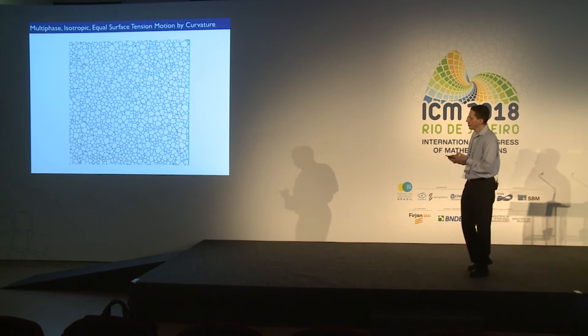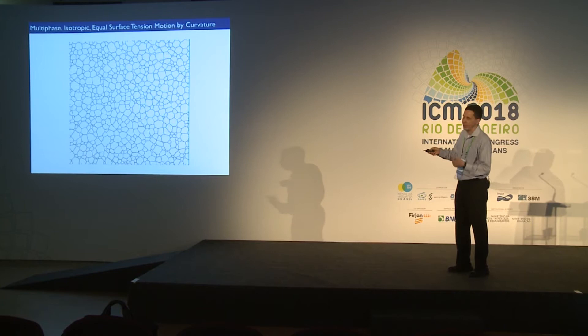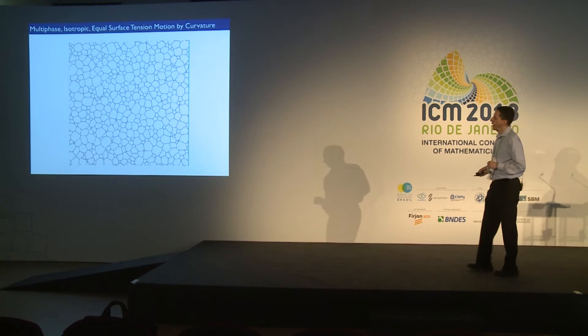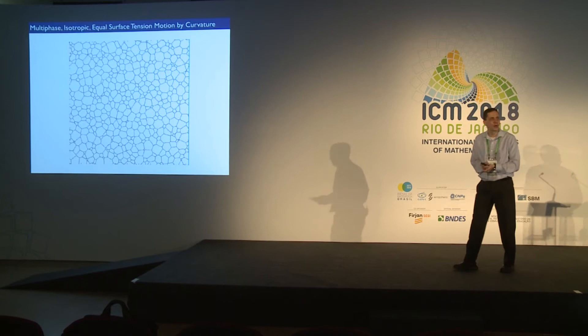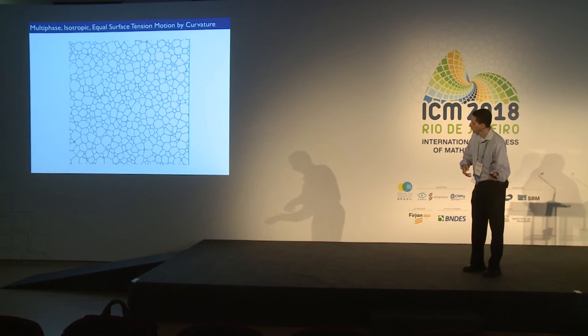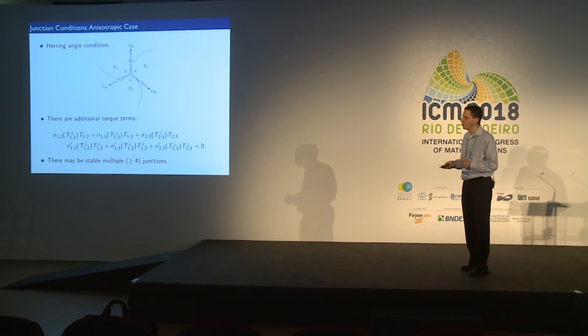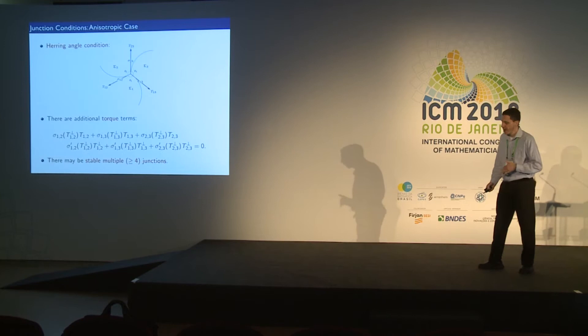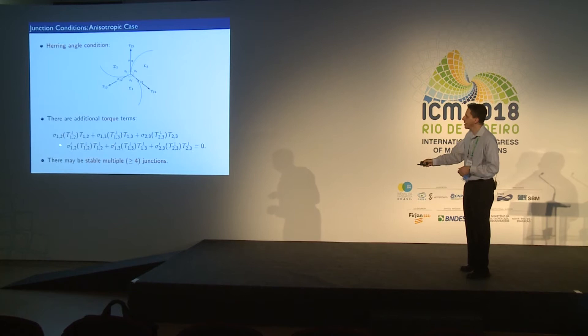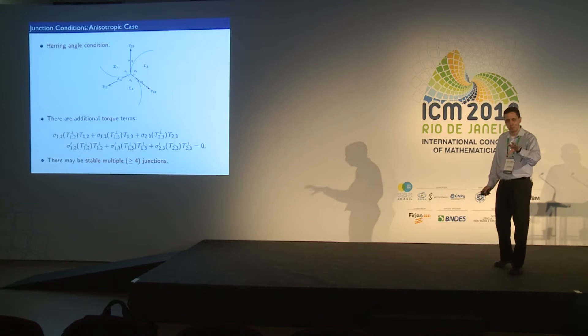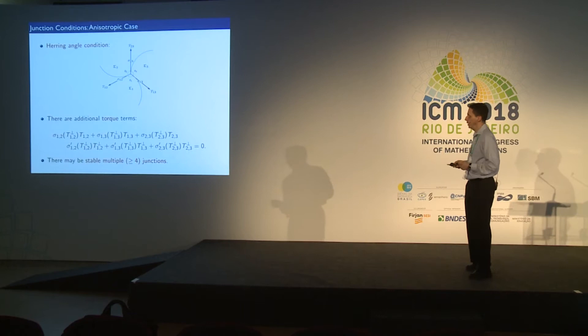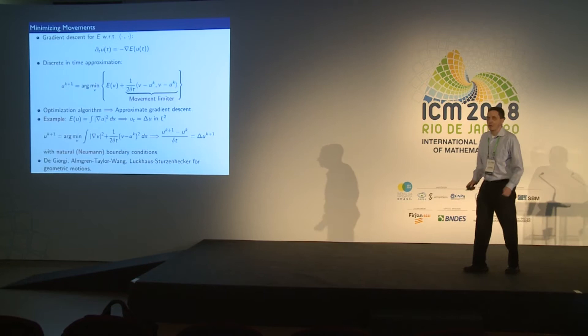Here is a simulation with many regions where all curves evolve by curvature motion and at triple junctions they try to satisfy the 120-degree angle condition. Lots of topological changes happen in between, and we're interested in numerical methods that can handle these topological changes in a reasonably simple way. In the anisotropic case where sigmas are functions of the normal, the condition at triple junctions becomes even more complicated — additional torque terms try to twist the configuration in the low-energy direction, and there may be stable higher-degree junctions.